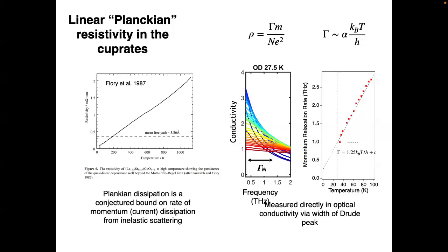One important scale is the lattice scale. This is where we would estimate that the mean free path of lanthanum strontium copper oxide becomes of order the length scale of the lattice constant itself. But the resistivity keeps getting worse, and of course it's nonsensical to think about scattering of particles on length scales shorter than the lattice constant itself. There's nothing in there. And so this is something that people have been trying to understand for a long time.